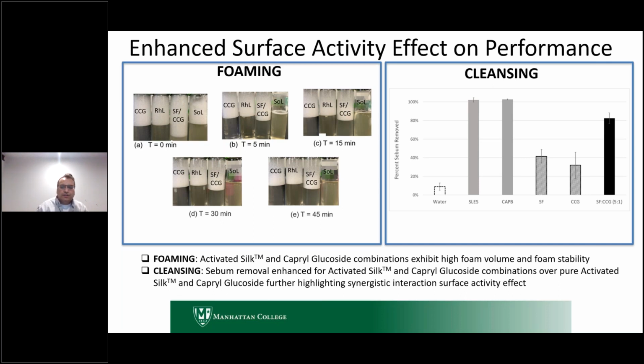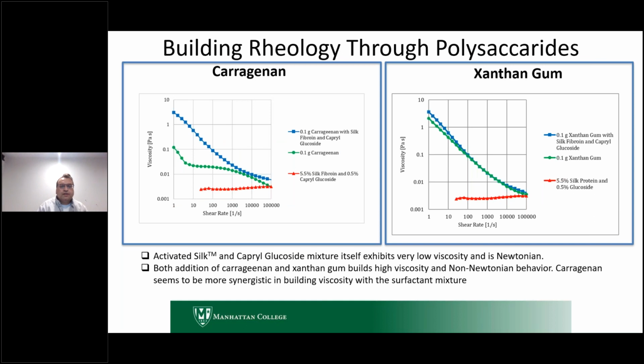So here we had to introduce a biopolymer. We introduced these carrageenans and xanthan gums, and we again optimized that formulation to get the right rheological profile for good sensory benefits, right? So we have to not only get foaming performance which beats everything else, and good cleansing, but on top of that, build up good viscosity, and not only viscosity, but the entire rheological profile, which gives rise to a very optimized sensory performance as well.